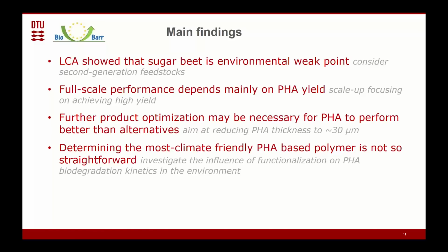Further product optimization may be necessary for PHA to perform better than existing alternatives. So reduction of thickness, if technologically possible, of course, is the way to go, combined perhaps with a different feedstock. And determining the most climate-friendly PHA-based polymer is not so straightforward, and that's because we know little about mineralization and biodegradation kinetics in the environment. That's one thing, but also because different metrics, different indicators can lead to different conclusions. So we need to be able to weigh them.